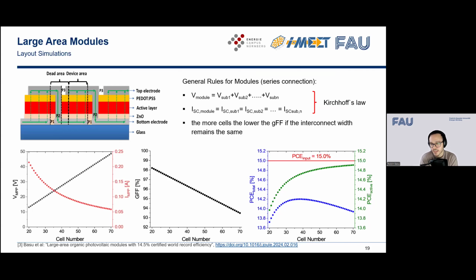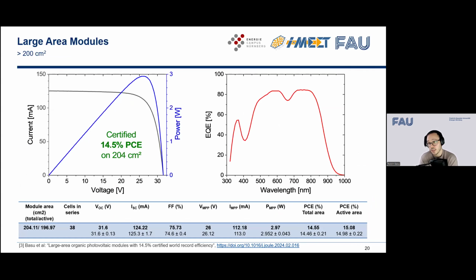And by that, you can just use CFD simulations to find out what is the optimum amount of cells to get the highest total PCE by simply balancing off the amount of subcells and the parameters that follow accordingly. So in our case, for the evaporated silver device, it was 38 cells. You can also tell by the graph on the bottom right that there is an optimum that exists. And that optimization allowed us to get large area modules that achieve the certified efficiency of 14.5% PCE on 204 square centimeters with quite high fill factors. So the layout optimizations and the coating optimizations help you to get very high efficiencies even on comparably large areas. But again, this is evaporated silver.